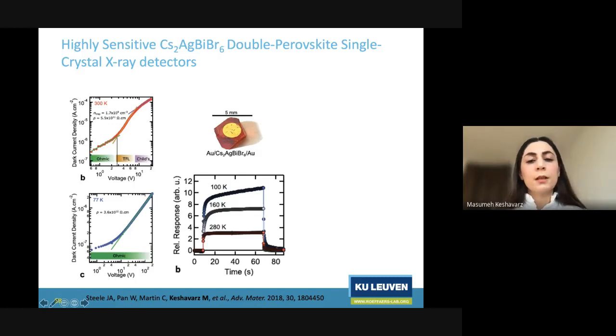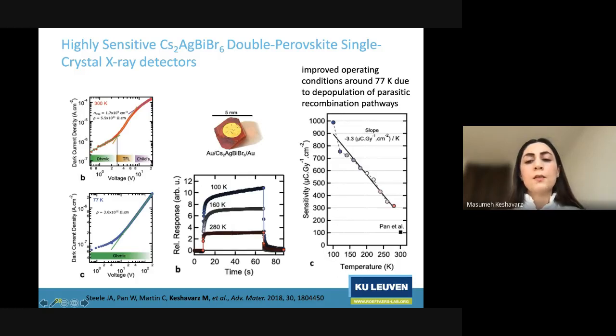Then we exposed them to X-ray and we measured their photoresponse. And as you can see, they have a large photoresponse upon X-ray exposure, and even much larger when you go down in temperature. So this is for pure cesium silver bismuth bromide.